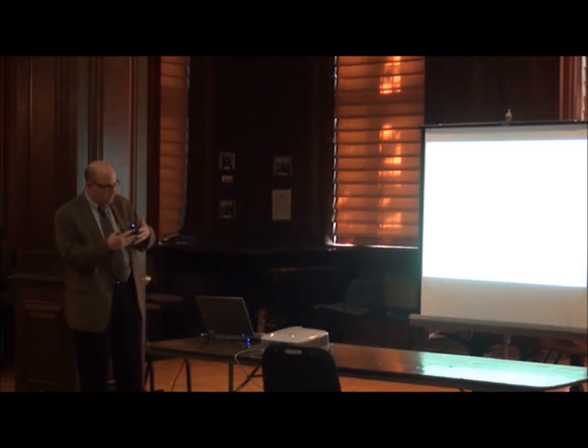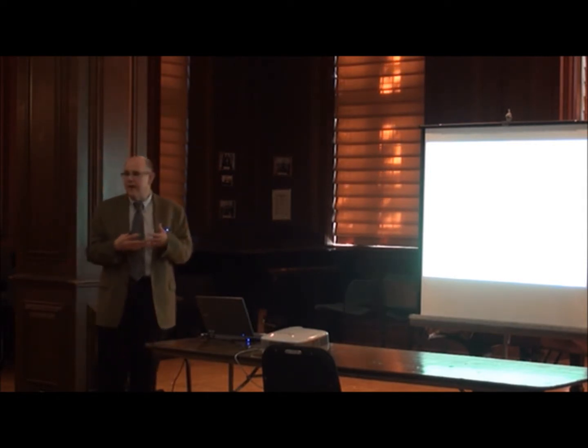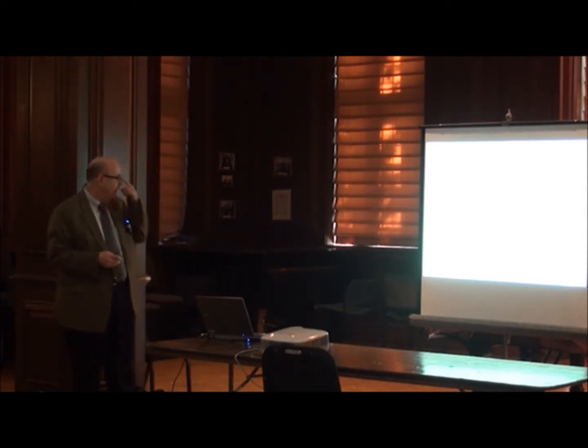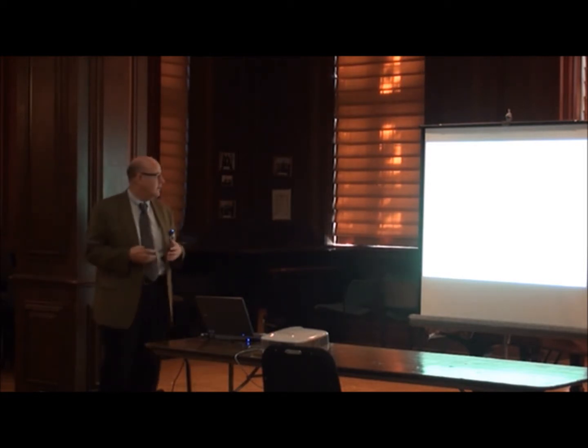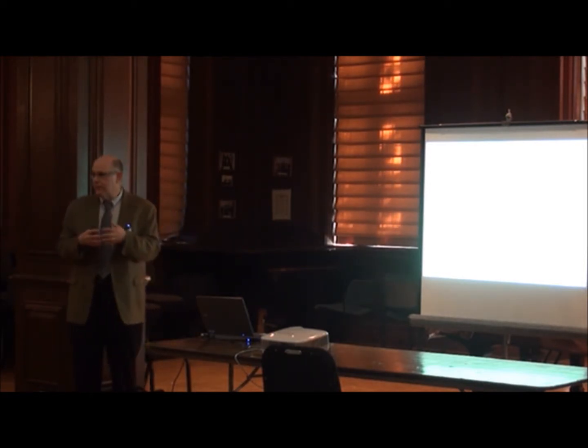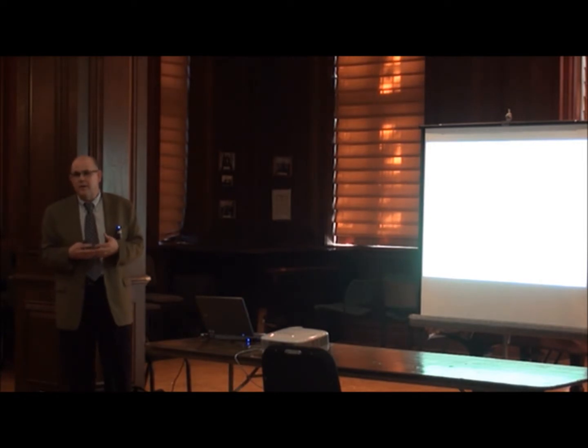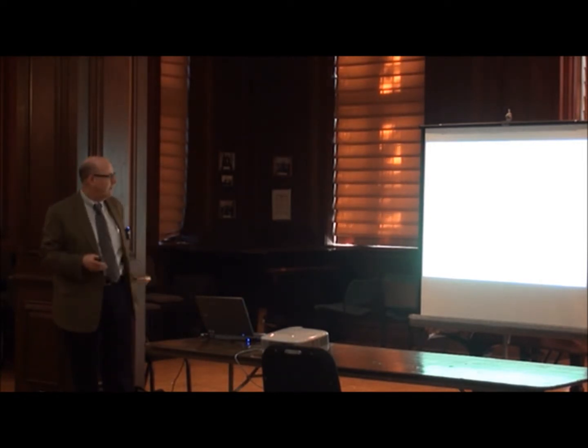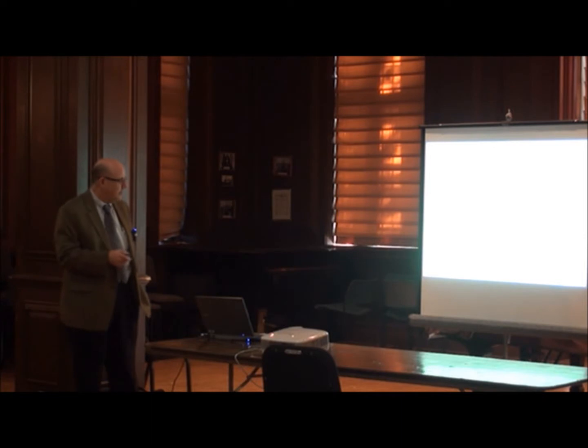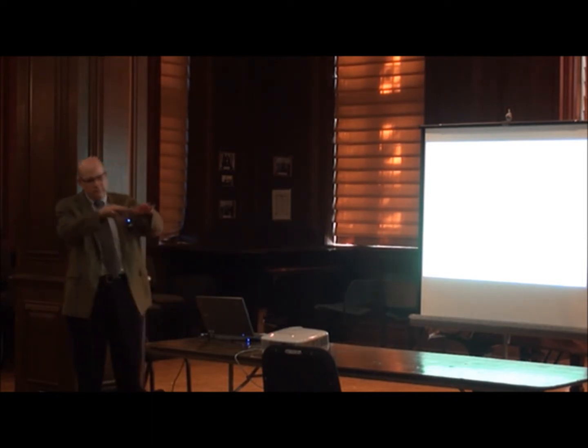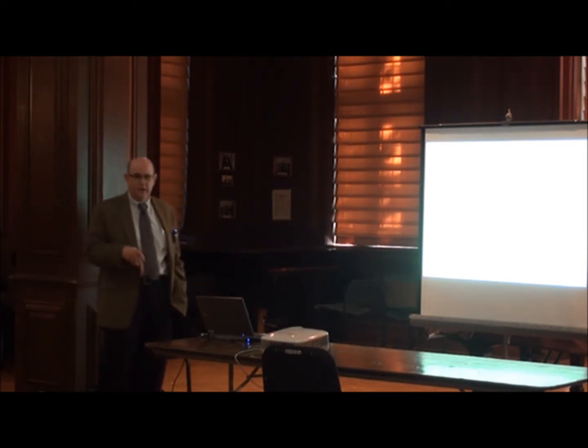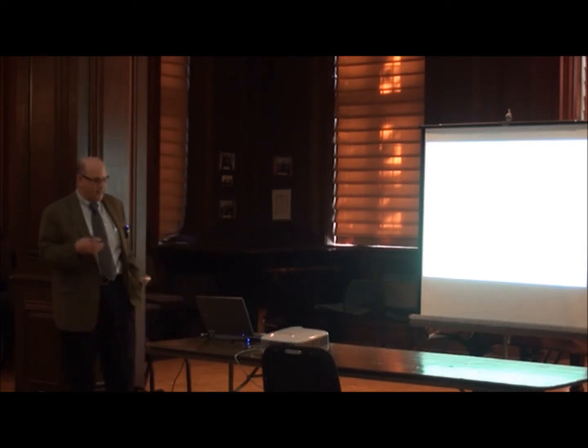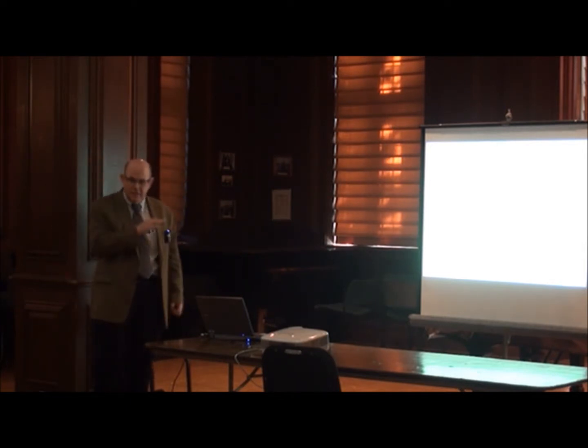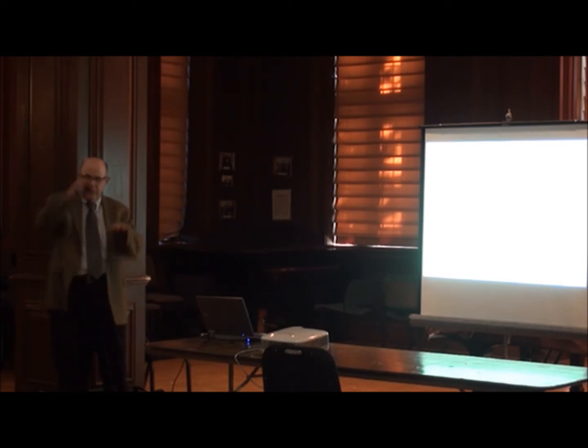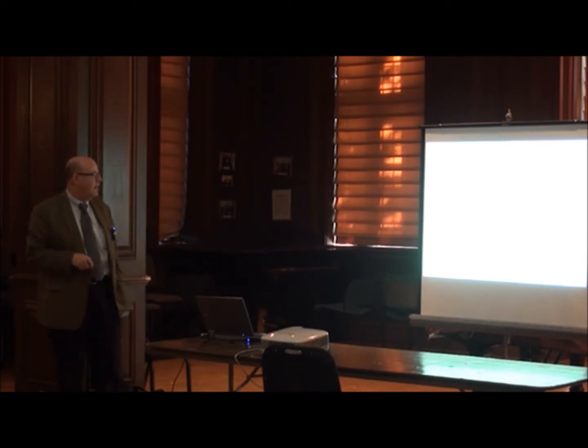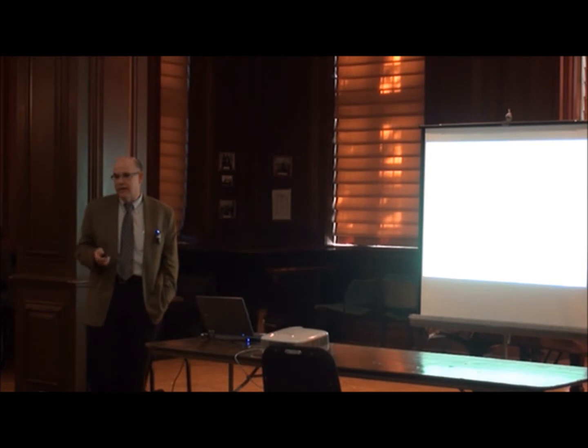You increase the force, yeah, sure enough, the real area of contact increases, so the friction increases. You make the material more stiff, a larger elastic modulus for a given force, I get less deformation of the asperities to support the load, so I get lower friction, in other words, a lower area of contact. If I have large summit radii, so big broad balloons, if you will, I'll get a large area of contact. And if I have a rougher kind of surface in this regime, meaning more of a distribution up and down, I'll get actually a smaller area of contact, and I'll get less friction.